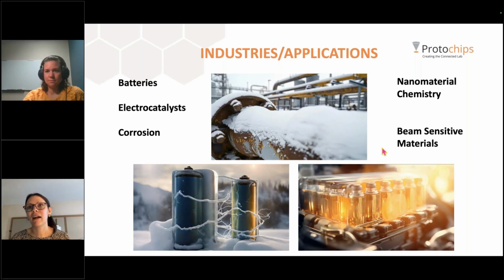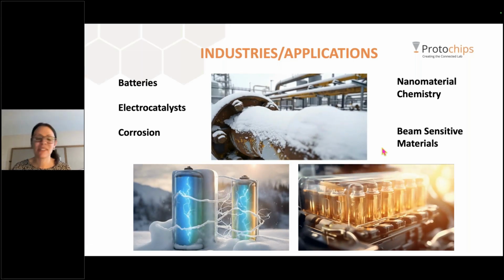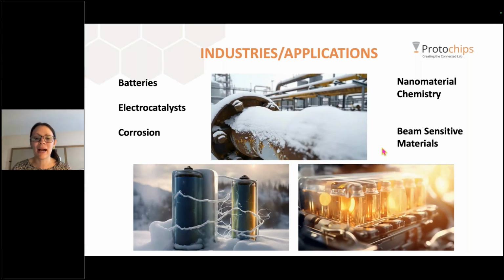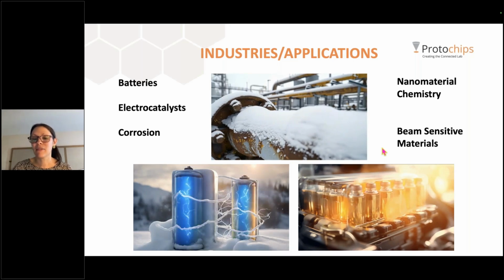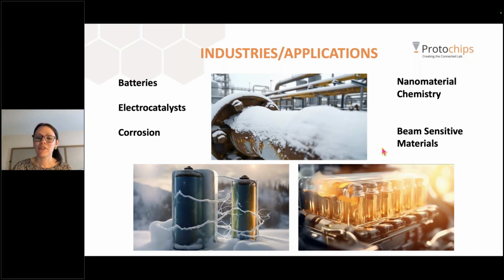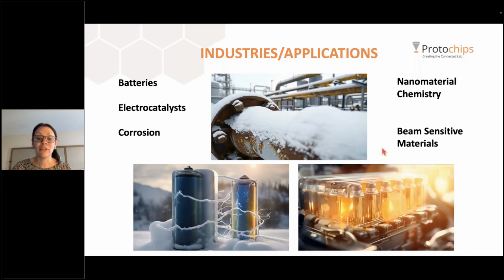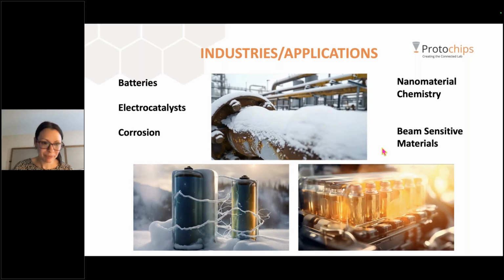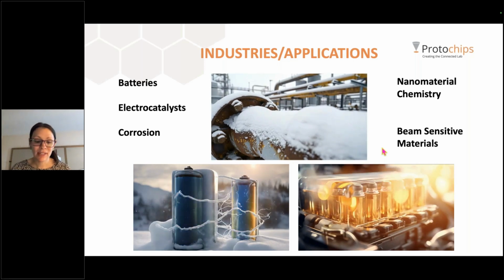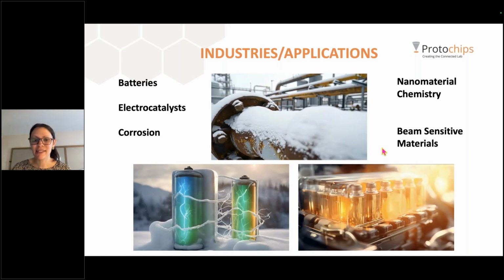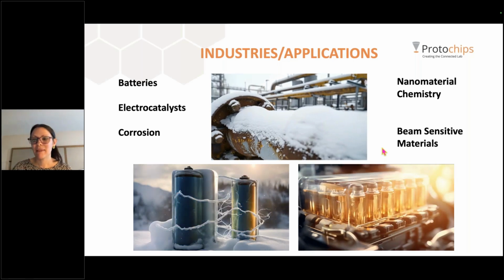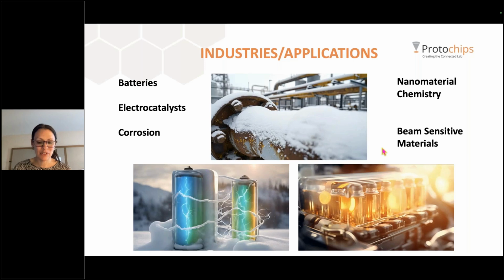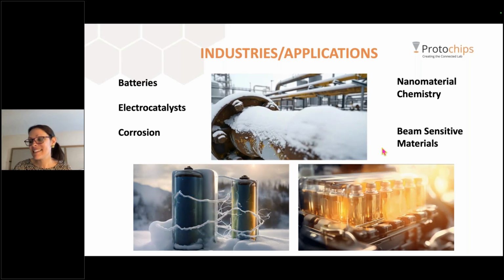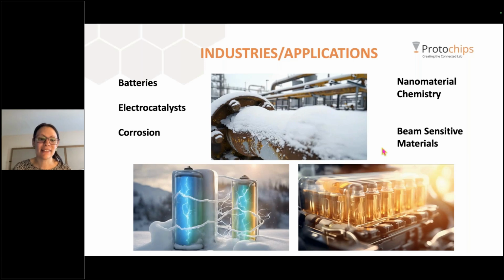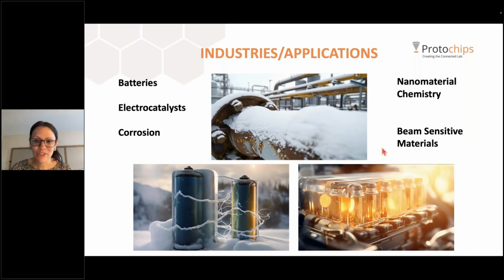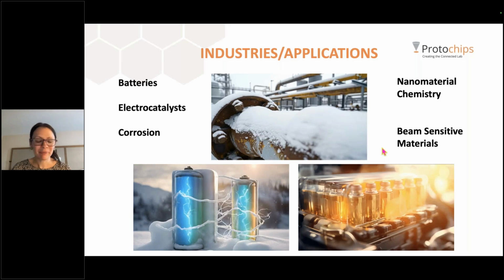Electrocatalysts typically operate at higher than room temperatures, 70 degrees C to 90 degrees C or so. Some are a little bit higher. And so again, we had a lot of feedback asking for more relevant temperatures for studying electrocatalysts in situ in the TEM as well. Corrosion. So corrosion is one of those processes, like corrosion of steels and alloys, let's say, a very, very slow process. You may be sitting down at the TEM in its natural time frame of days, weeks, months on end. And so if you increase the temperature, you can make that reaction happen a bit quicker.